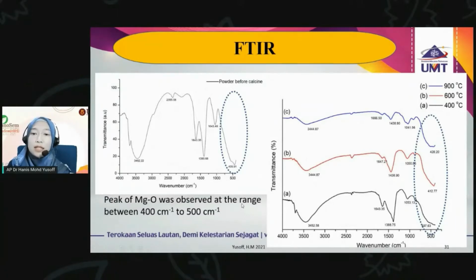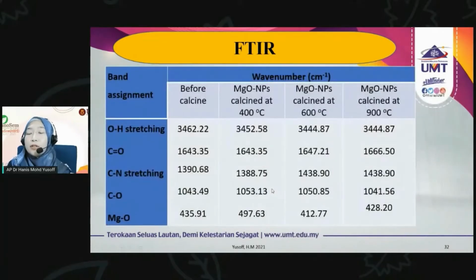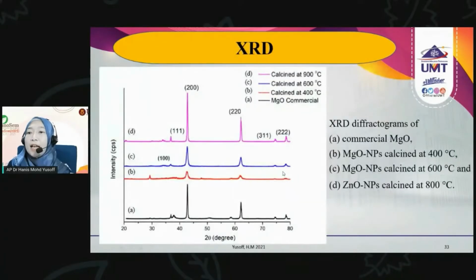And the most important characteristic when you're dealing with a metal oxide is the metal oxide range here, around 400 to 600, and this is due to the adsorbed water molecules. So it's quite common for magnesium oxide nanoparticles. Okay, so these are the band assignments, and followed by XRD. So it is comparable with the commercial and with no other impurities, and we have referred to the JCPDS and PDF reference as well.